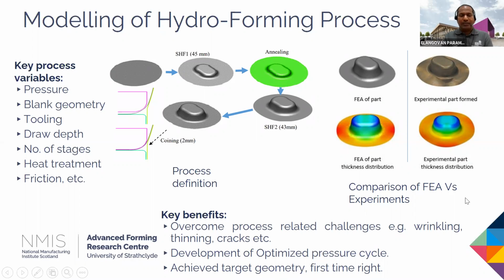And finally we come up with a process definition, as you could see in the center of the slide. So we start with a blank geometry, and then we form the part to about 45 millimeter in stage one, and then we introduced the intermediate annealing process, and then finally we form the second stage. Then finally we introduced another process step mainly for the part requirement. In order to achieve consistency in the flange radius, we have introduced the coining process step. And on the right hand side of the slide, you could see the comparison of FE and experimental work. We could see there was a good agreement in terms of the thickness distribution for the formed part.